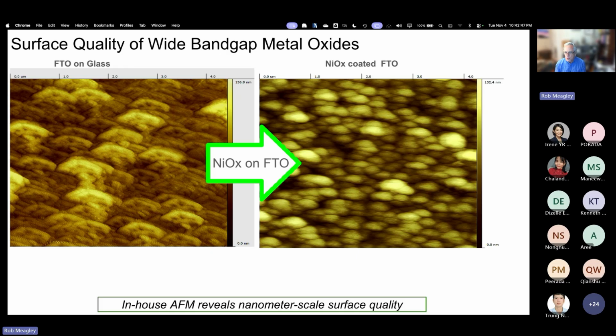Very often in the semiconductor world, you'll be looking at silicon on insulator or other semiconductors on insulator. Certainly in the solar industry, we're engaged in making thin film solar, so glass is our substrate. With charge control on the surface, we're able to see fluorine-doped tin oxide all the way down to the individual facets and defects in the crystals, small amounts of secondary crystallization on the surface that was then coated with a nickel oxide.